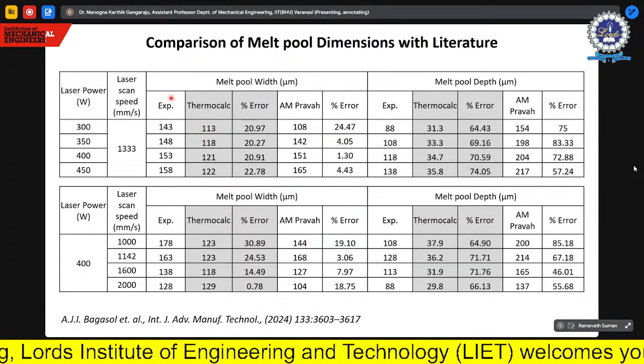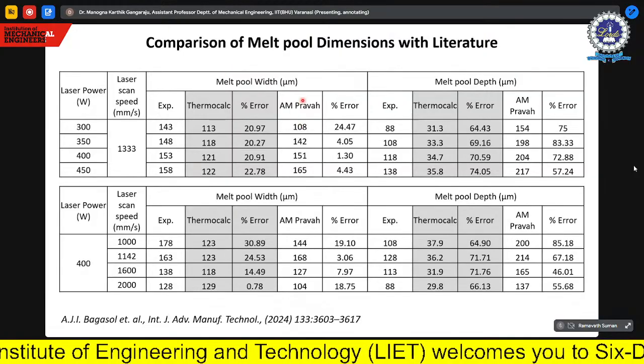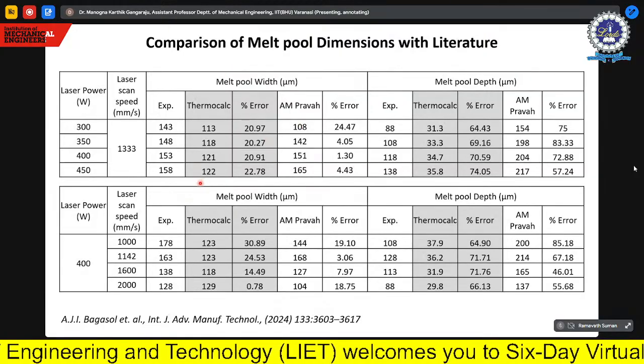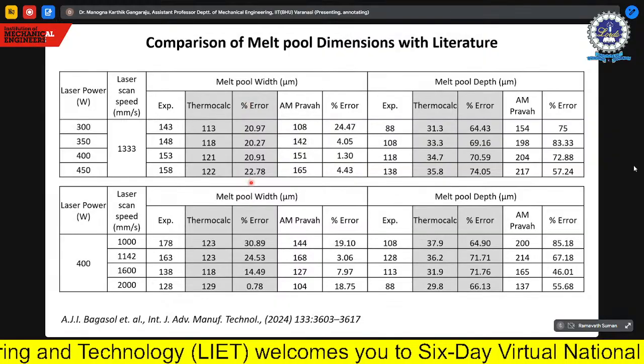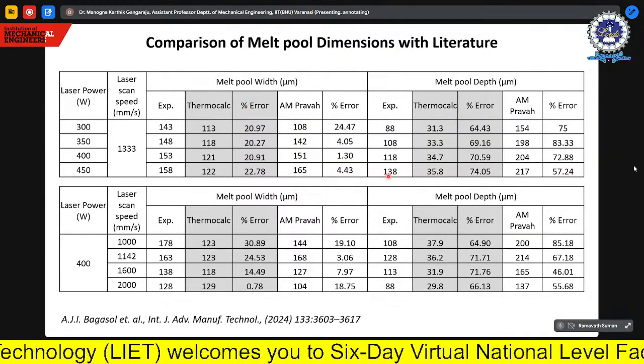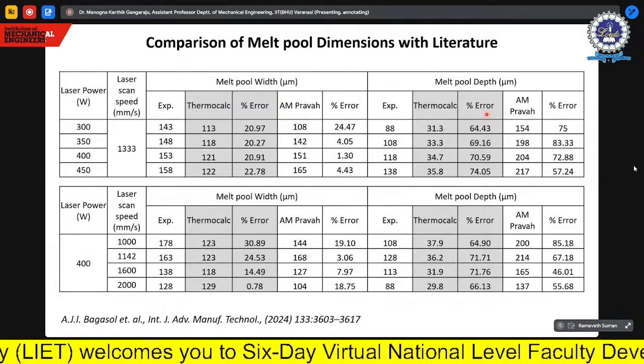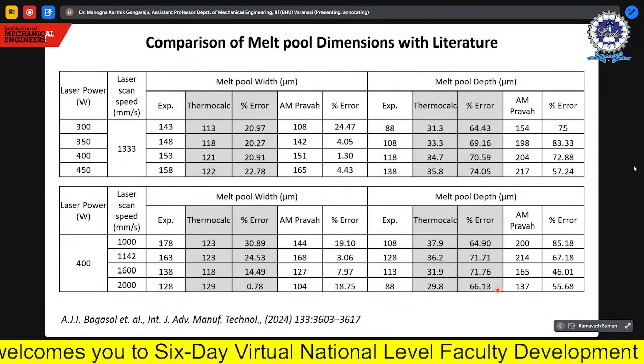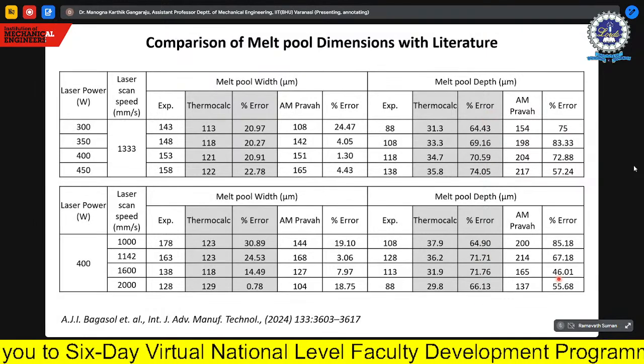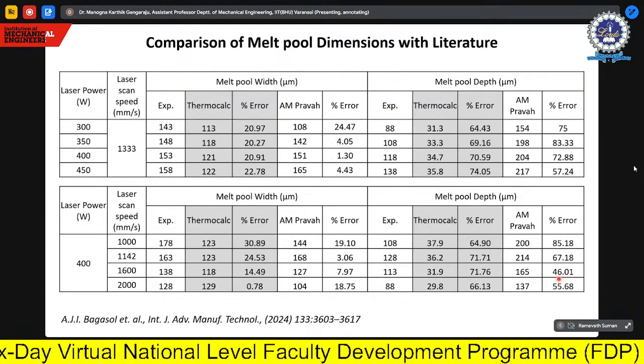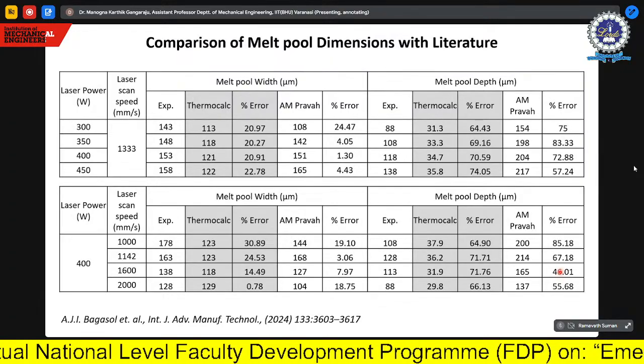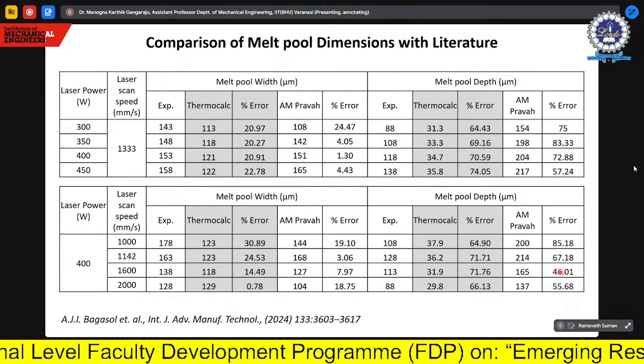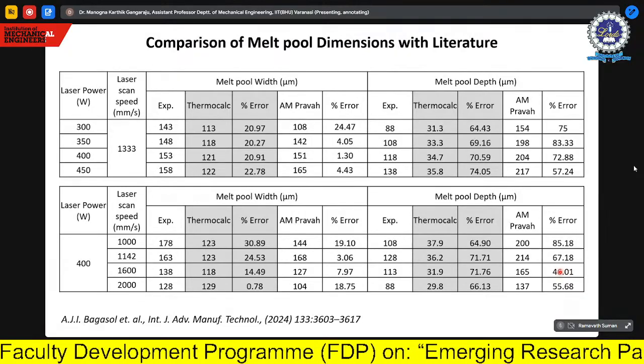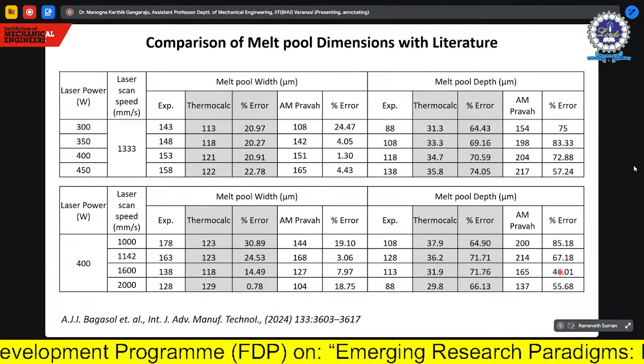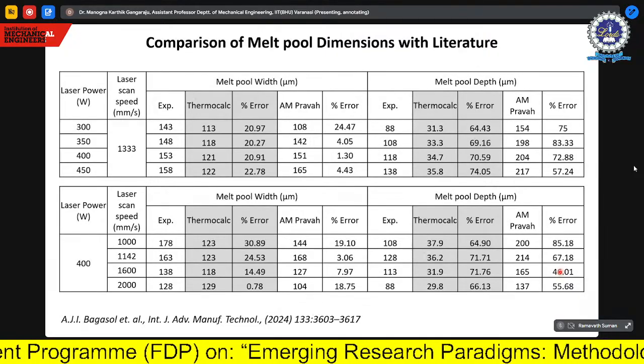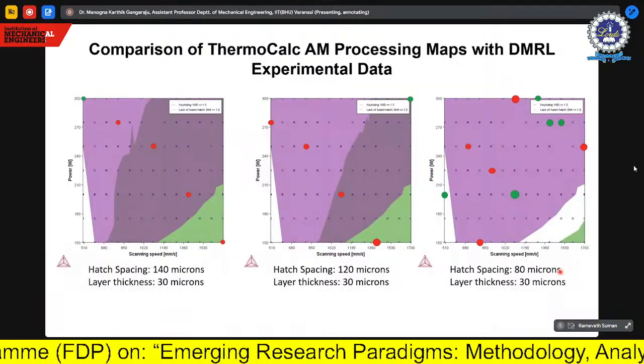So these are your experimental data and these are your software information. We are getting close to 20% error with respect to width in both the software. But in the case of depth, we have a very high error, close to 60% in both of these software. So currently we are optimizing this software so that we come very close to the reality, the experimental data.